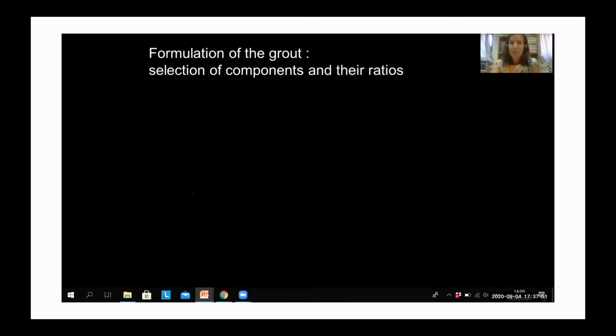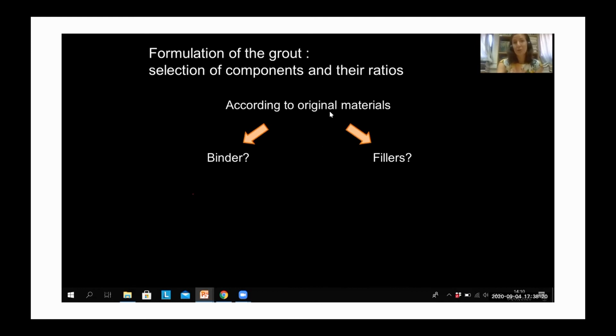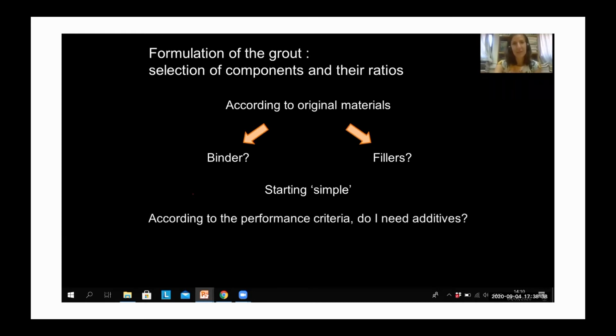So I will talk today about grouts with different, separate components. For this reason, we can talk about formulation of the grout. So we mix it, we choose it, we do it, in terms of selection of components and their ratios. We said that we do this keeping in mind what the original materials are, what the stratigraphy is, what the composition is. According to this, we may have a lead to choose a particular binder and particular fillers and aggregates. And usually you try to start simple, meaning that you don't try to overcomplicate your formulation immediately. And then according to performance criteria, I think, do I need something more?